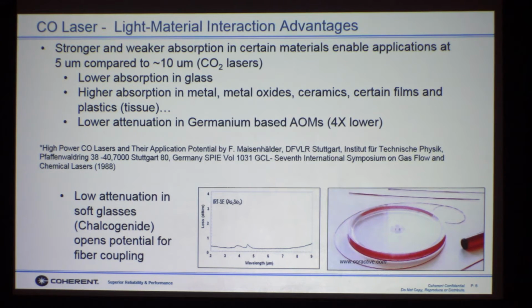Another really interesting potential for 5 microns is the potential to fiber couple it. Okay, so the holy grail for CO2 has always been to fiber couple it, right? And it's been the Achilles heel against the fiber lasers in the past. And the reason is that there's so much absorption in most of the materials. Chalcogenide glass is one material that people have made fibers out of that has very, very, very low absorption in the 5 micron range. And so there's real potential to be able to fiber couple this CO laser.